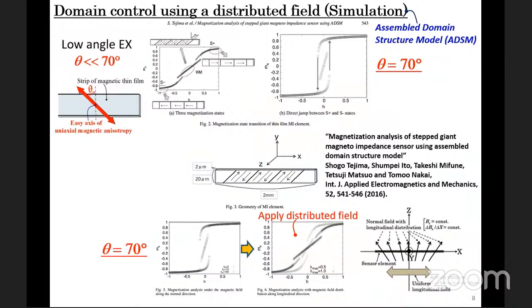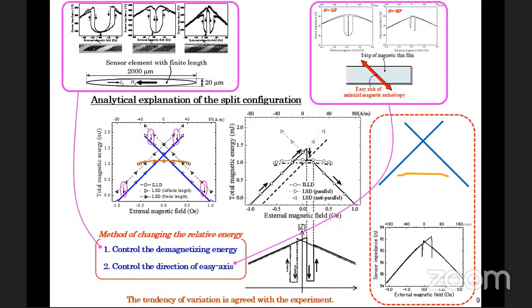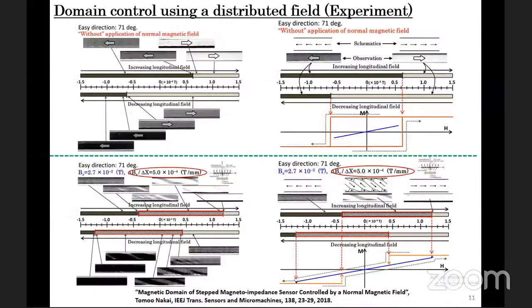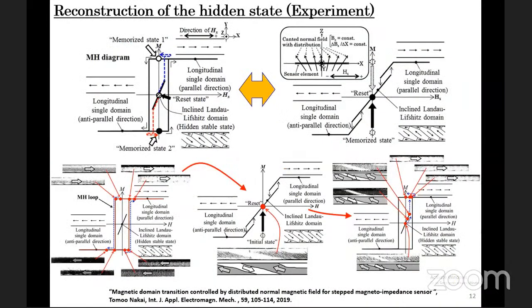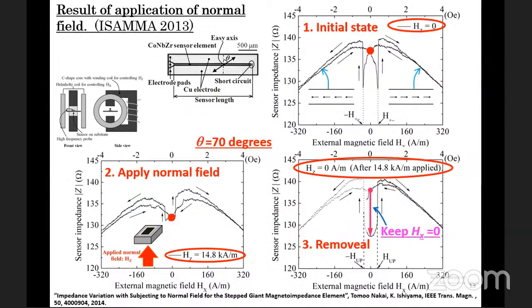This magnetic state transition was also simulated by a domain structure analysis. The assembled domain structure model, ADSM, was applied to this element, and we obtained the same results as shown previously. It was a collaboration with Professor Matsuo, Kyoto University. We have carried out many experiments as follows. As a result, we can say that the artificial transition to the hidden multi-domain state was confirmed and established for this element.